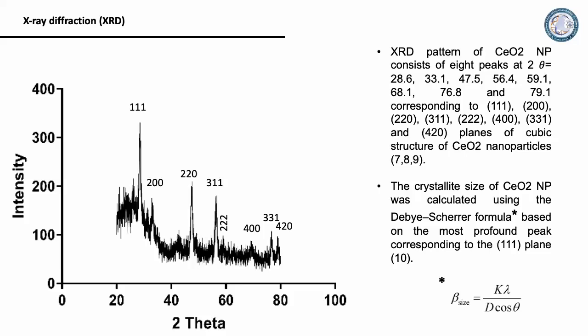In the X-ray diffraction pattern shown in the figure, the peaks at 2 theta values are consistent with the literature. Furthermore, the crystallite size of cerium oxide nanoparticles was calculated as 30 nanometers using the Debye-Scherrer formula, based on the most prominent peak corresponding to the 111 plane.